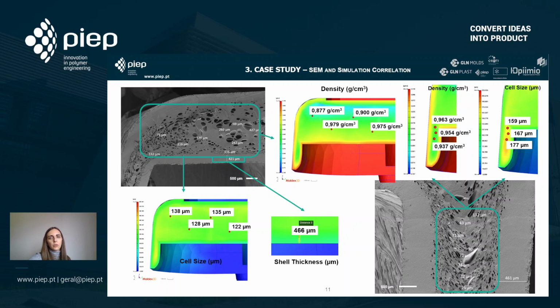However, when we go on to the density of the part, we can clearly see some differences. We can clearly see a tendency of the results. Here we can see that the shell has a higher density of material, and when you go on to the core, you have lower densities of material, and so you can conclude that there is a formation of some kind of cell structure throughout the part. However, it still cannot accurately predict the variation of density throughout the part.